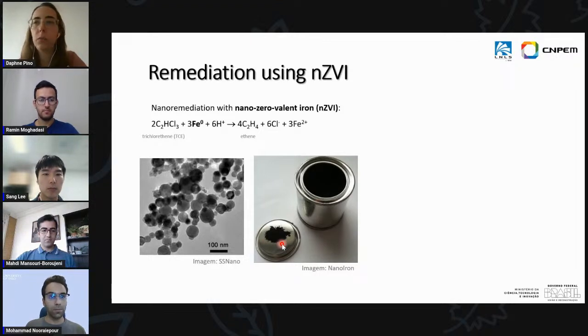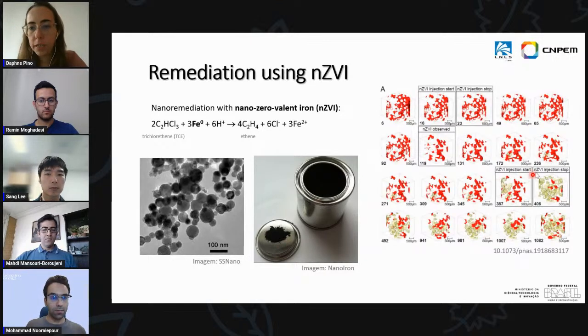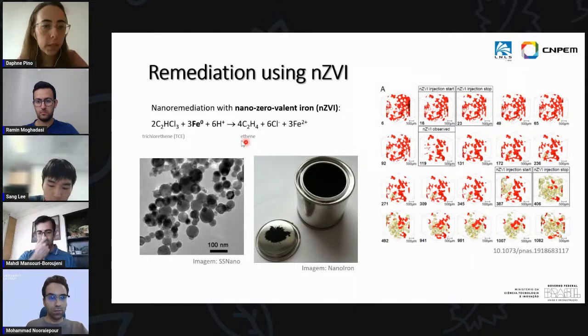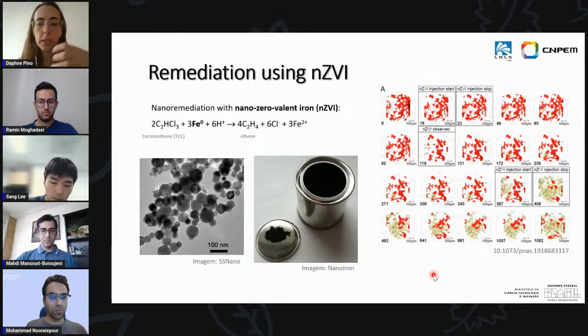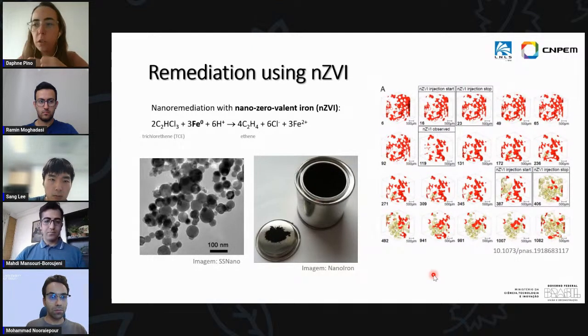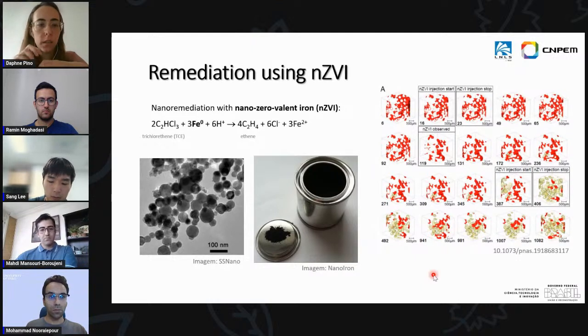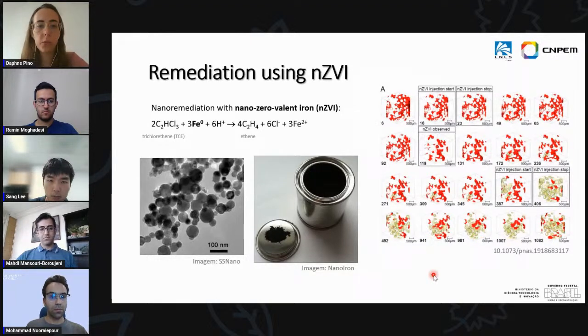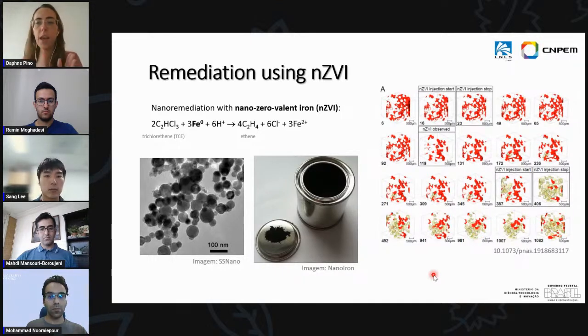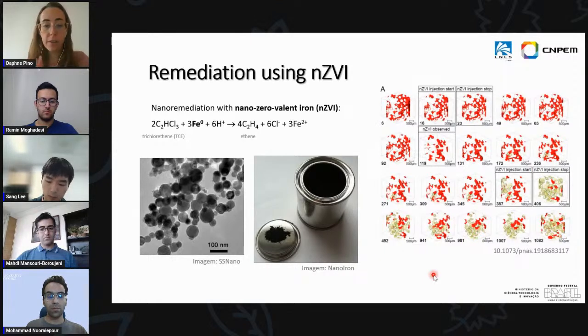We want to see how exactly these reactions are happening at the micro scale. In a published paper from our group, the red areas show the TCE solvent. After injecting nanoparticles, the yellow part is gas produced during the reaction. We saw consumption of TCE, and the gas was also displacing some of the solvent droplets. This could only be done using synchrotron light — not only to see things at a very small scale, but also to image the process at different times, giving us resolution in time. You can almost make a movie of what is happening in your sample during an injection experiment.